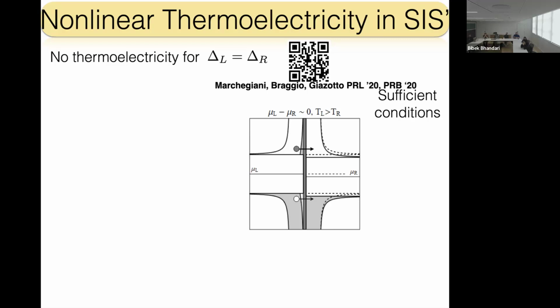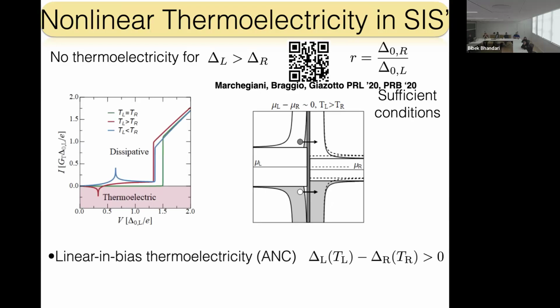And the reason why, because if you make the computation, you realize that when you shift the chemical potential, you see essentially that the quasi-particle tunneling changes, reducing, and also this reduces. So in a certain sense, due to the symmetry there is a sort of exact cancellation. And this is exactly the question before. This is a completely particle-hole symmetric system. We are just a little bit shifting. So you are in the linear regime, you cannot get any thermoelectric effect. That's it.